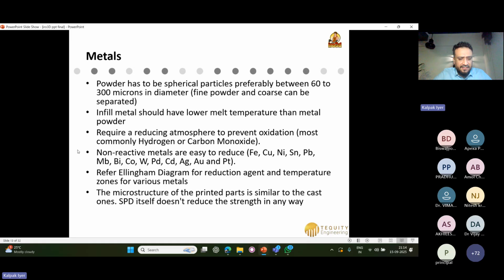So the build powders that can be used are these materials: iron, copper, nickel, tin, lead, molybdenum, bismuth, cobalt, tungsten, palladium, cadmium, silver, gold, platinum are examples of non-reactive metals. They can be good choices for build powders. And for reduction reaction, anybody interested in this field, I'm sure some of you might be, please refer to something called the Ellingham diagrams. Anybody from a metallurgy background will be well versed with it. An Ellingham diagram basically gives you the right amount of reduction agent to be added and at what temperature the reduction reaction will take place.